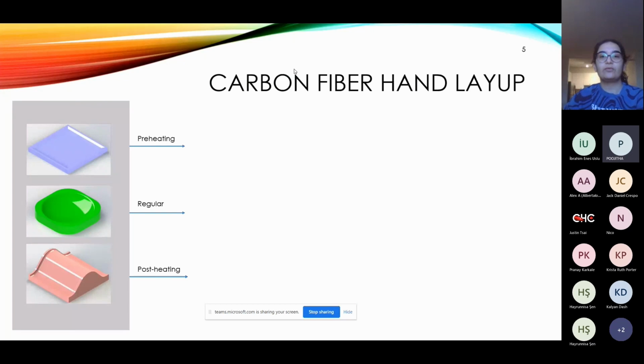Knowing the material that we were working with, the team decided to experiment with molds, infusion, and layups. In SolidWorks, 3 different 3D pattern molds were designed: the flat plane, the female hemisphere, and the arc. Each set was subjected to one of 3 curing conditions to determine the most optimum curing setting. The decision was based on rigidity and curing time. The molds were optimized to eliminate any sharp edges, to avoid air pockets from the layups, to reduce stress concentrations, and to allow for easy removal from the molds.